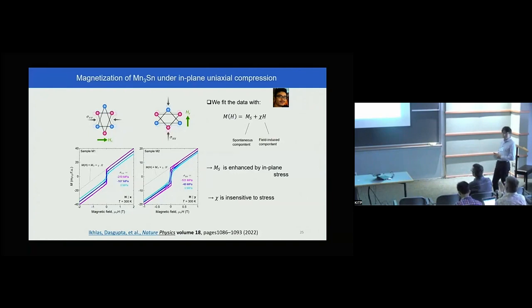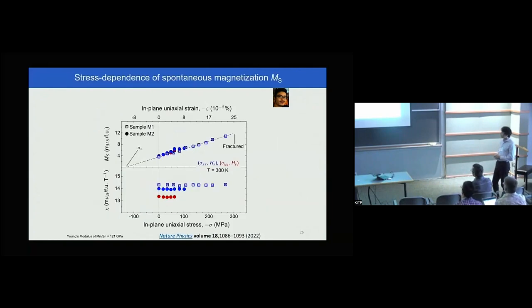Is there a distinction? In the case of this tensile stress effect, there are a number of triangular lattice materials which exhibit magnon-phonon coupling, and they are known to be multiferroics. Is there something special which allows you to switch the magnetization, or should they all exhibit that? I just didn't quite get that.